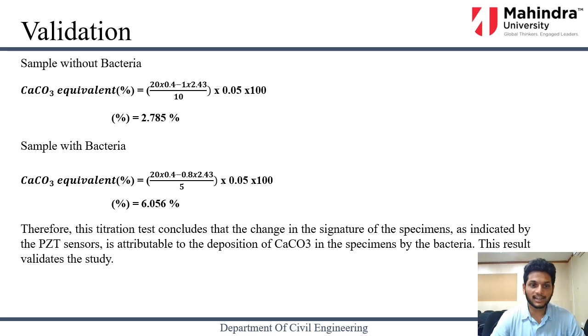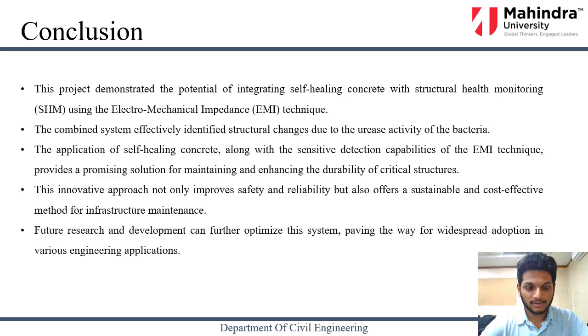Therefore the titration test has concluded that there is an increase in the calcium carbonate percentage, and that is due to the presence of bacteria and the bacterial action. So by this we can say that the project has demonstrated the successful integration of structural health monitoring techniques using the electrical impedance technique, and has noted the minute changes which are caused by the bacterial action. The application of self-healing concrete can also be used for the prolonged life of structures,